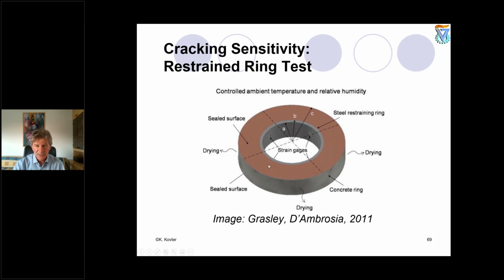And then concrete starts hardening, and the deformation of shrinkage results in the generation of stresses. We have radial and tangential stresses. This is very well known. It's explained in our papers and in the papers of these authors and many others. So this is very easy to calculate. We can do both autogeneous shrinkage in restraint conditions test and drying shrinkage.